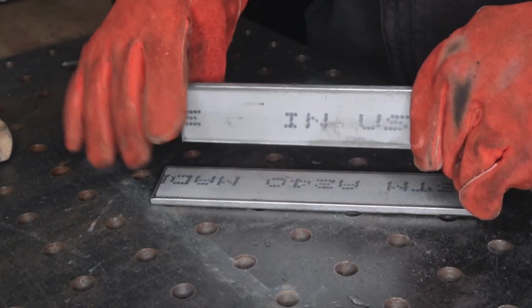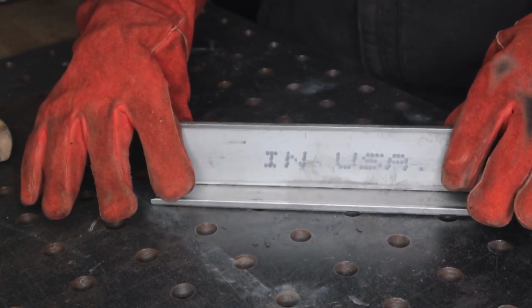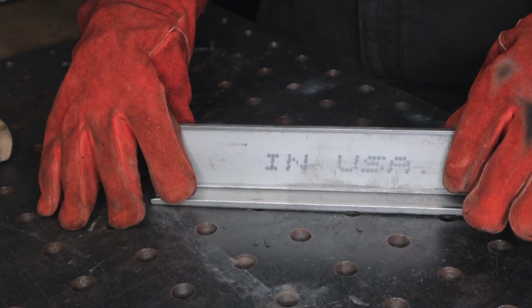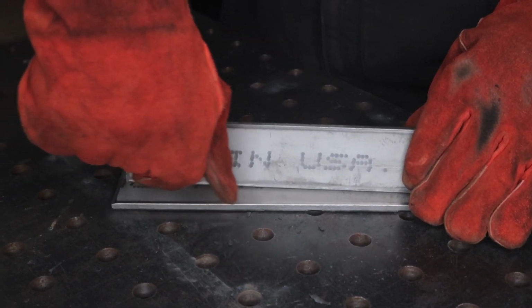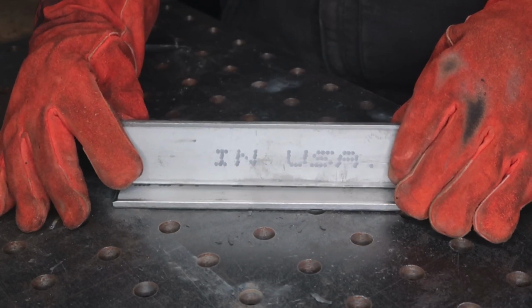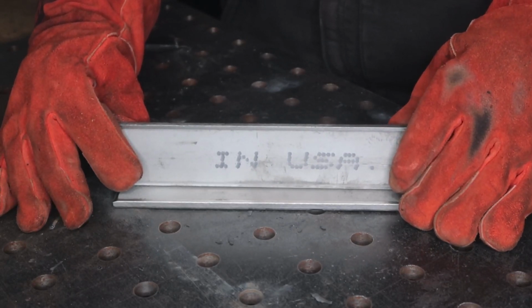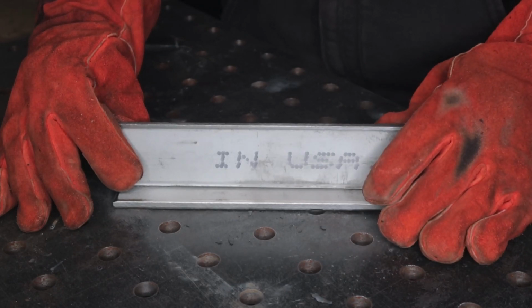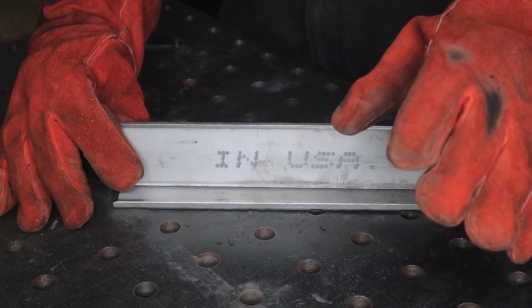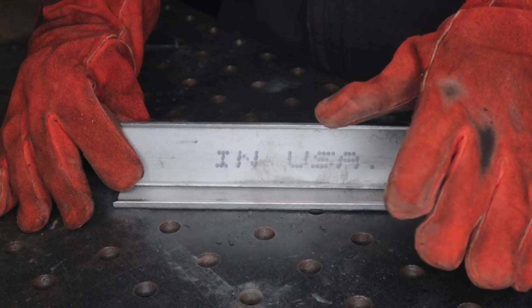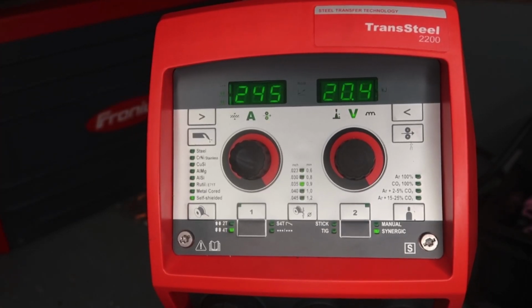Let's step it up a notch and do this quarter inch horizontal fillet weld with self-shielded stainless. I'm gonna do the same position, drag, but we are increasing the wire feed speed to 320 inches a minute, which is around 17.5 volts. Now keep in mind, when you're using this wire, you can weld 300 series stainless, but also some 400 series stainless. I kept my contact tip to work distance the same as the flat lap joint in the prior weld test. And we're running about a 15 degree drag angle at 245 amps at 20.4 volts.